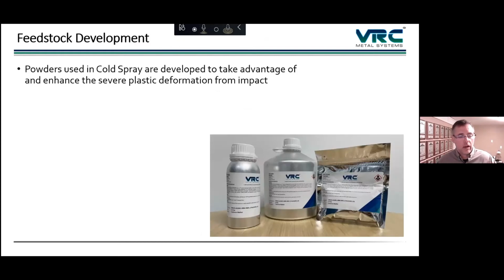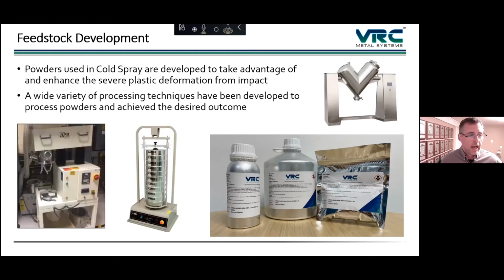So in order to get all these effects correct, we actually have to have special powder. Just like every other industry, you want to have powder that's tailored to the process. So that means particle size distribution, but it also means things like microstructure, because this is a relatively cold process, so we try to affect the microstructure of the material as well. And we also blend materials, we granulate materials, we do lots of things to get the particles into the right condition so that when we cold spray them, we get these high quality bonds as well as interparticle bonding.